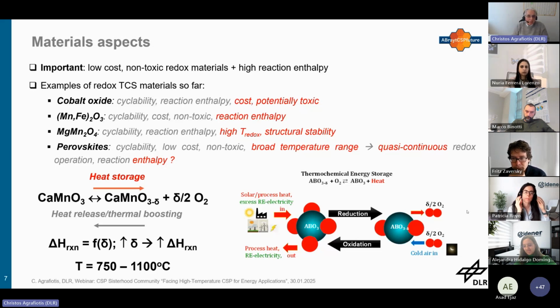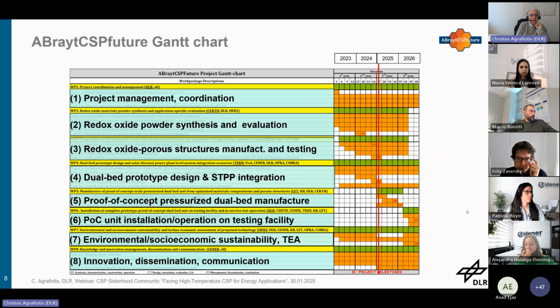Calcium manganite is the most studied family for this class of materials. And of course, one can play with the composition to improve several characteristics. The operating temperature range is between 750 and 1100 degrees when reduction and oxidation take place.